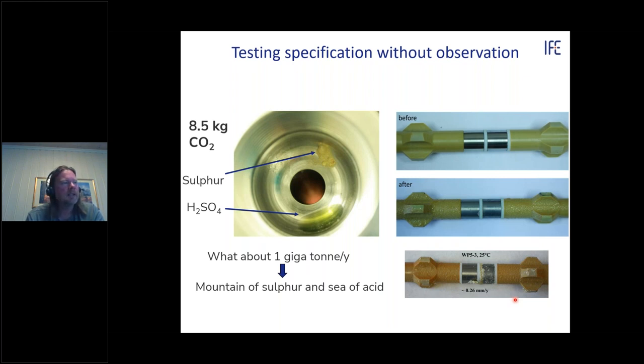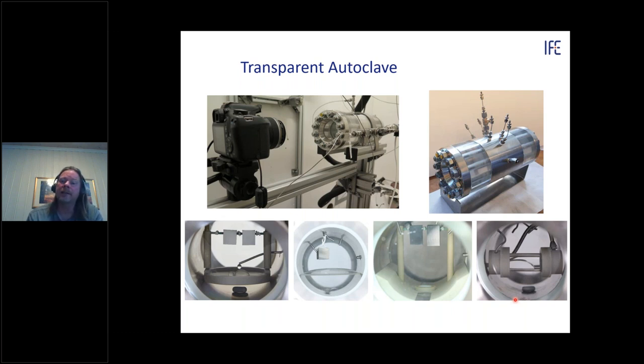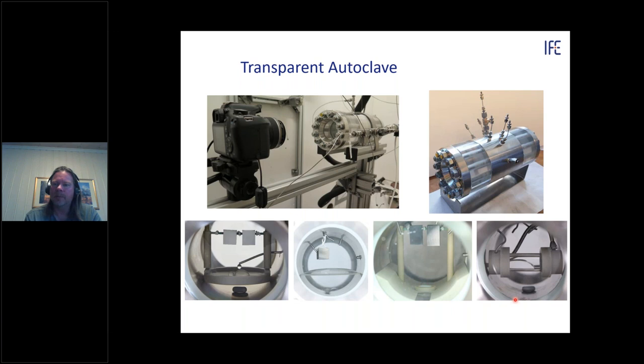To find CO2 impurity limits we needed something more, and that is when we started using a transparent autoclave capable of running up to 200 bar of CO2. A camera takes pictures assembled into time-lapse video, allowing us to visually observe whether acid is falling out or corrosion is occurring on the coupon. This allowed us to screen many more cases in a shorter time.